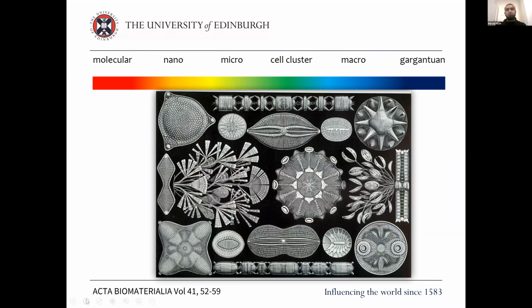You've got cylindrical ones, you've got long, thin ones, circular ones, you've got weird shaped ones. So diatoms come in all sorts of shapes, and the important thing here is that they secrete this sticky glue, and that they form a bioglass skeleton that is one of the strongest natural materials on Earth. It has a strength that was measured at around, I think you find the paper in PNAS, at around 1 gigapascal, which is pretty good for a natural material.